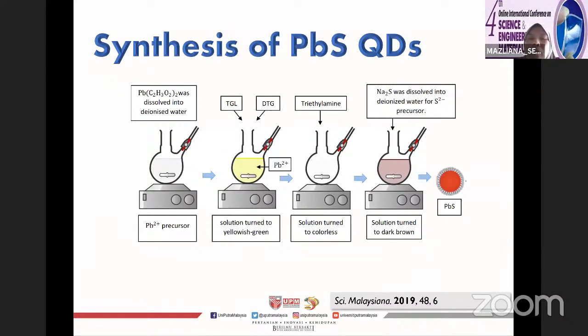At the same time, we prepare the sulfur solution in a separate vial. Then we mix the lead precursor and the sulfur precursor together, and it forms a dark brown solution, which shows the formation of the PbS quantum dots.